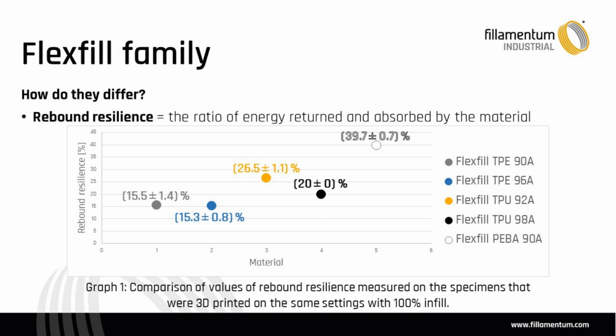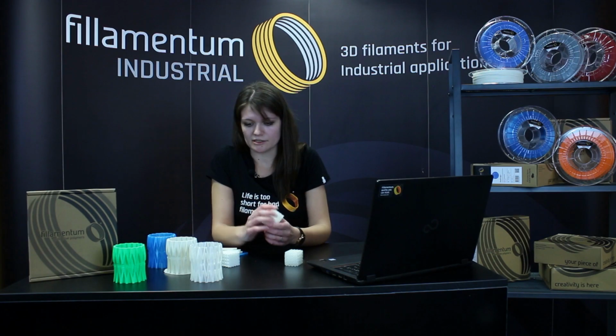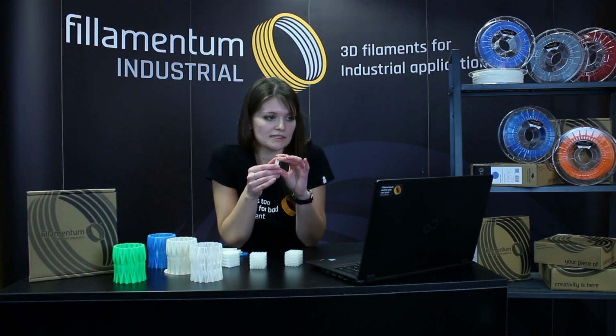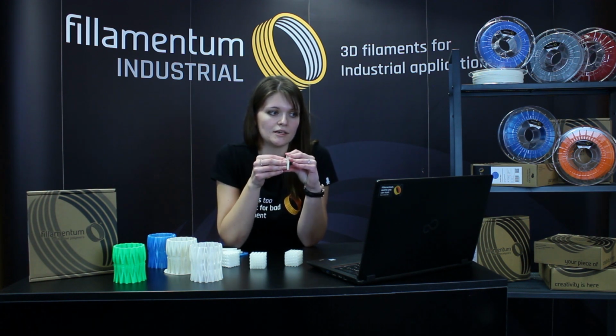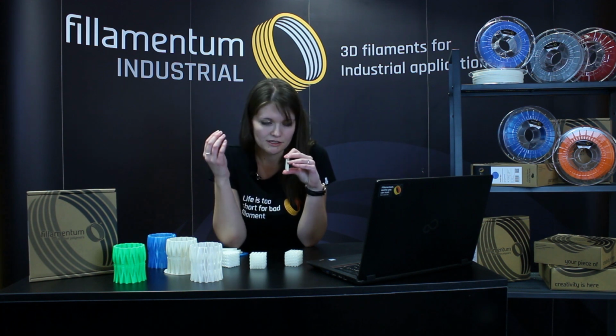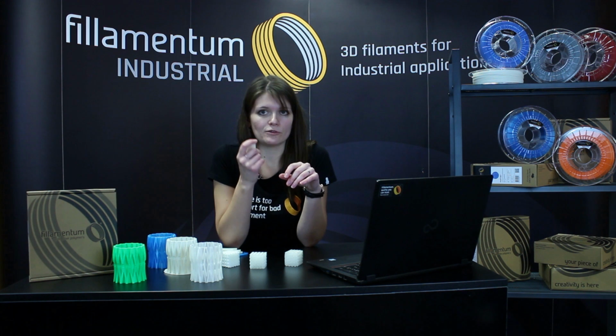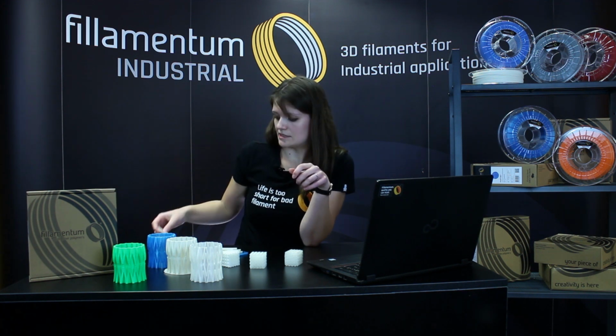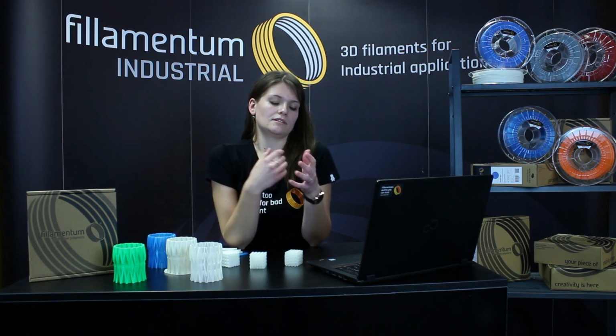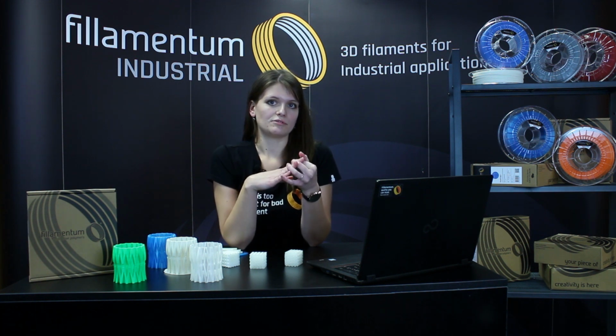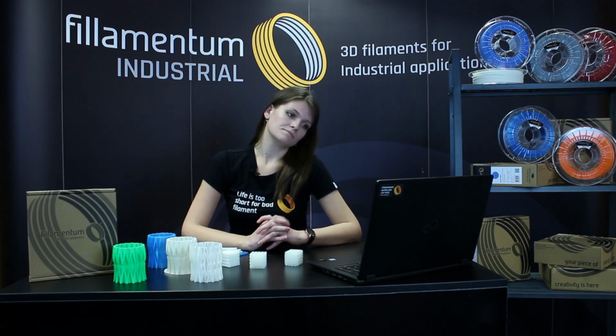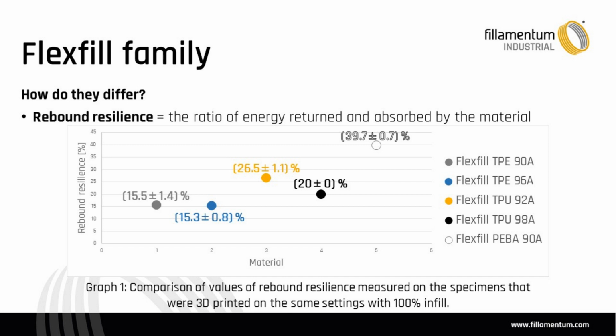On the graph there is the comparison of all 5 Flexfills, and rebound resilience is the ratio of energy that is absorbed or returned by the material. It's measured on this kind of specimens, and when the pendulum loads the specimen, the percentage of the energy that is returned is shown on the graph. So for example, PEBA has 40% of energy that is returned and 60% of energy is absorbed. And in comparison, TPE has about 15% of energy returned, so therefore TPE and also TPU is better for damping applications, and PEBA is perfect for applications when you need vibration transfer.